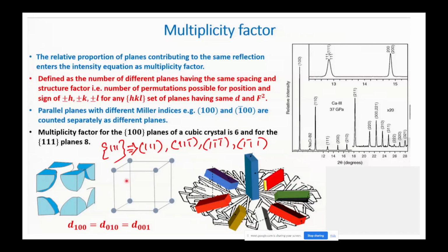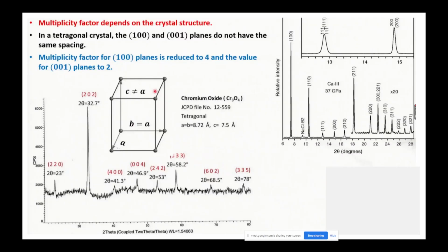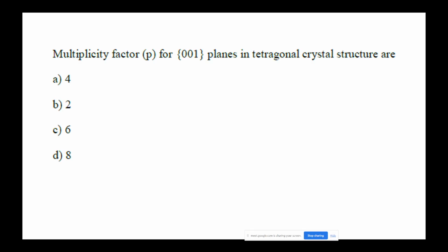Okay, in this slide you can see what multiplicity is and how it can be calculated. It is nothing but the proportion of planes contributing to the same reflection that enters the intensity equation as the multiplicity factor. For the cubic, if you take a 111 plane, then this factor will be 8. For 100 it is 6. Here also for 100 planes it is reduced to 4, and the value for 001 planes is 2. So 6 and 4. Multiplicity factor for 001 plane, as I explained, is 2.